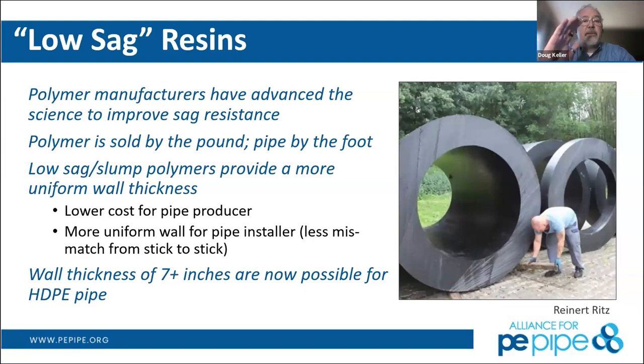So you don't have to be concerned about finding Humpty Dumpty's low point on the pipe and aligning those all up together. So what we're able to see now is that we have less mismatch in wall thickness between sticks of pipe, and wall thicknesses greater than 7 inches are now possible for high density polyethylene pipe. And on the right, you see a picture of Reinert Ritz, who's a European producer, and you can see how thick that pipe is. If we assume that gentleman's head is probably like 10 inches from his chin to the top, that's a pretty significantly thick pipe that is possible to be made. Next slide.